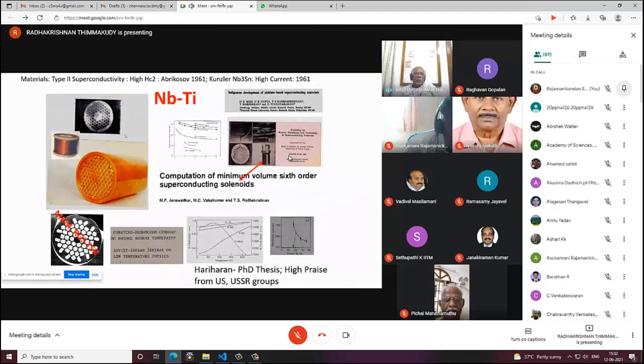So all that electromagnetic response of superconductors came up with a solution that you need to make superconductors into fine filaments. For example, a wire that is about half a millimeter in diameter, which is enough for a copper wire that you can wind into a coil, is not stable as a magnet. So you need to put in it a number of filaments of about 30, 40 microns each, and that is possible in fabrication. You make use of copper and small niobium titanium rods, and then co-draw it, and this is the kind of cross section. You can see the number of filaments in a copper matrix, and if you go on drawing through dies, you can get a thin wire.